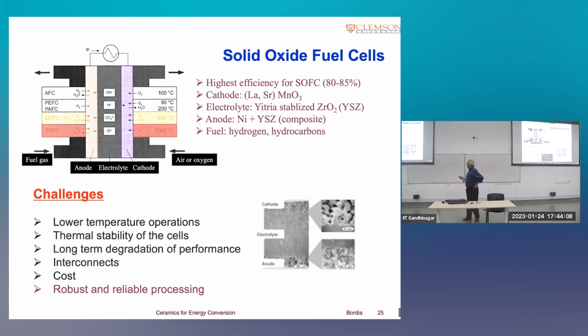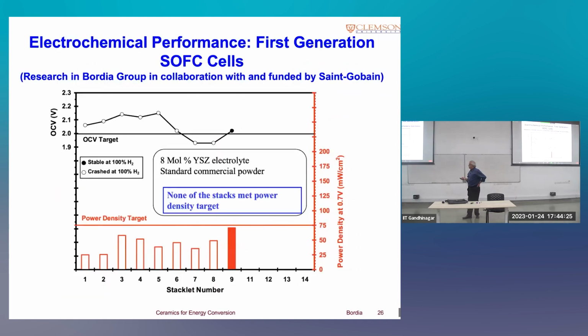And the efficiencies are very high, up to about 75 to 80%. And there's a lot of interest in them, also a lot of challenges. So we have been working on their processing, and I'll show you the final set of results on this rather long project that we did with a company. This was a company that we worked with, Saint-Gobain. It's a big French materials and glass company, with big operations in India also. And they were making these solid oxide fuel cells, and for all of them that they made, there's a whole stack of about 10 or 20 stacks, the performance was below their target, where they would have pass-fail criteria, both for their power density and for open circuit voltage.